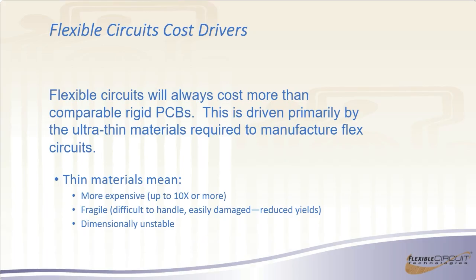Flex circuits are also very dimensionally unstable, which can throw a lot of loops when you're trying to stack up very, very tiny pads on internal layers, and then be able to drill a hole through them and make contact and get the registration that you need. And what makes it even more interesting is that the materials can grow and shrink by 1 mil per inch just with temperature and humidity, and they don't grow and shrink in the same ratio in the X and Y axis. So trying to calculate what's going to happen can be interesting too.